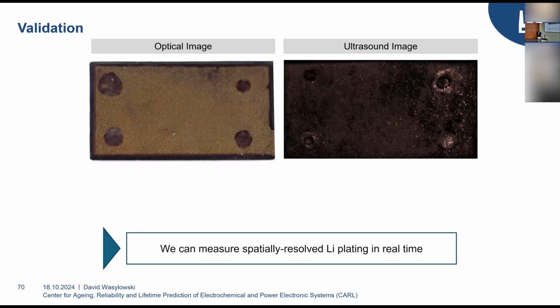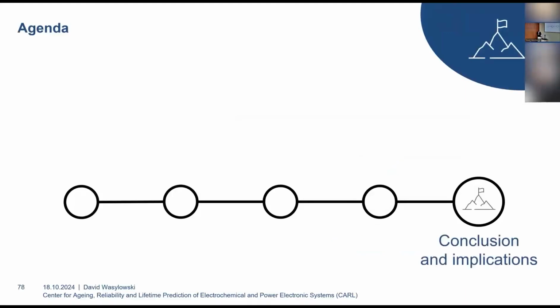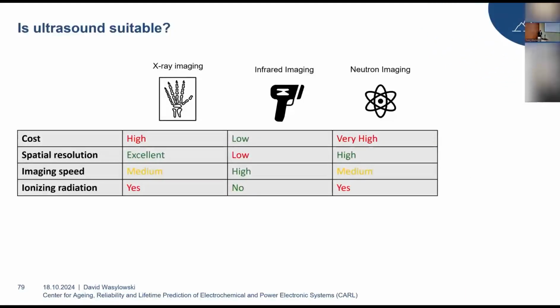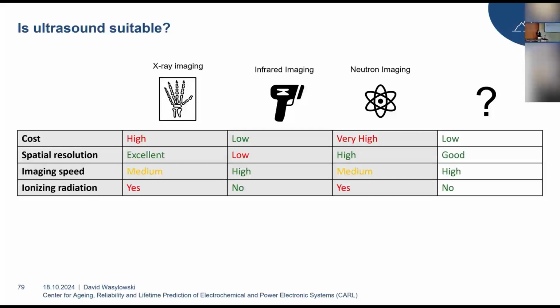So in conclusion, did we fill this gap that we were trying to fill earlier? So did we find a measurement method which is low cost and generates images which are meaningful for us in an acceptable time? And I think the research suggests that the answer is mostly yes. So we have obviously this very low-cost design that I showed you earlier, and we have this spatial resolution of 75 micrometers that we demonstrated in the second imaging phase.